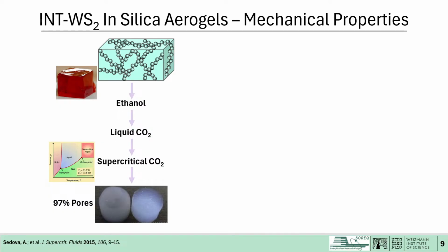Those materials are used for insulation. They are lightweight, about 97% pores, so they can, for example, be used in aerospace without compromising the weight. Nonetheless, they suffer from poor mechanical properties. So we said we will add nanotubes and see if we can improve the mechanical properties without compromising the weight, as we're adding nanomaterials, and without compromising the pores. The aerogel without the nanotubes is white and transparent, and with nanotubes it becomes gray.